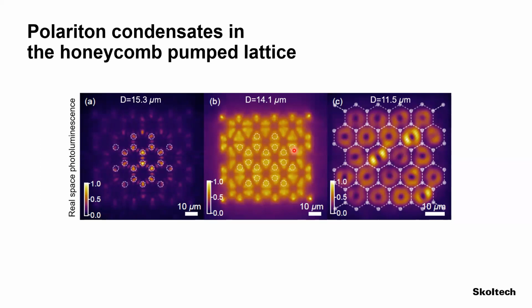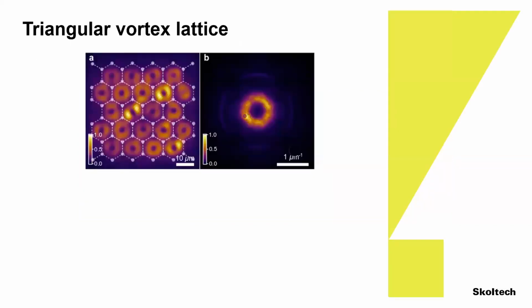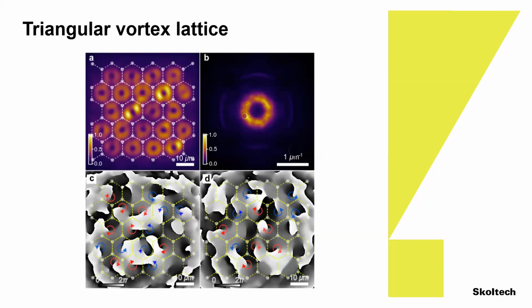Okay, now, do I have vortices? Well, if I look at reciprocal space, I see most of the emission is in a ring. So I have non-freestanding polaritons. All polaritons rotate around in the reciprocal space. If I measure the phases, I see that stochastically from realization to realization, I see different spin configurations. And if I now go to the next step, this is just what you observe when you inject this lattice